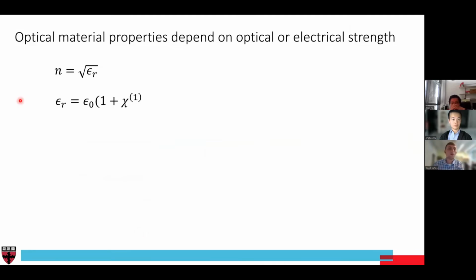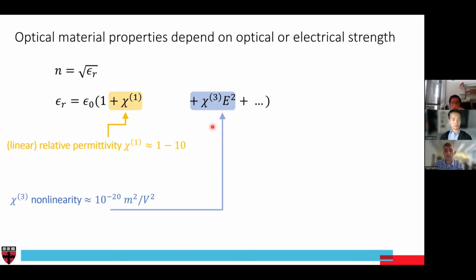But here, very briefly, the refractive index of a material is given by the square root of its permittivity, certainly at optical frequencies. And this permittivity value is dependent on a variety of different components. One is the linear relative permittivity, something on the order of 1 to 10. All materials will also have this nonlinear component, this chi3, that's dependent on the intensity of the electric field that's within the material. So if I increase the intensity of the light, this tells me that the optical properties will change, but very weakly, because this parameter is about 20 orders of magnitude lower than its